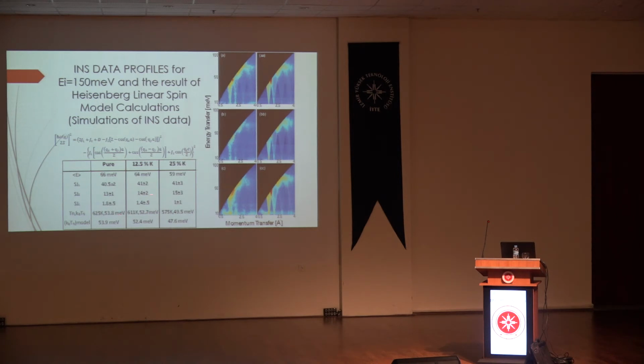For 12.5, we have those, and for 25%, we have those values. The second number over there is the antiferromagnetic transition temperature, Néel temperature: 625, 611, and 575 Kelvin. As you see, when you dope the material, you lower the TN values, which is all okay and expected. The corresponding number is the Kelvin to millielectron volt conversion, the same number. The third number is the one that I calculated for the temperatures.